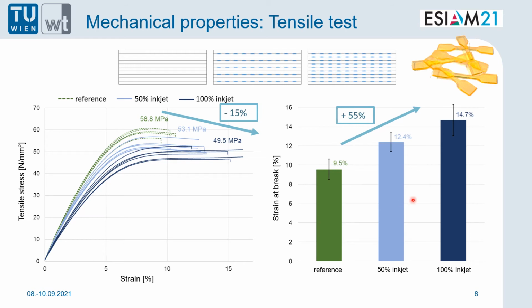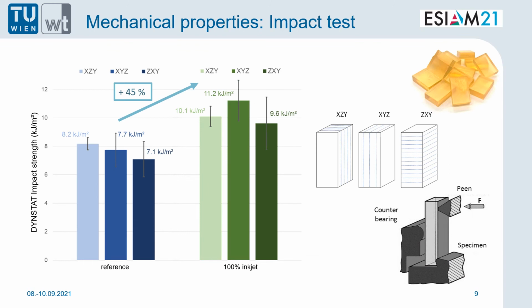We jetted different amounts of ink inside of the parts and observed a linear behavior with increasing ink amount. While tensile strength was reduced by 15%, an increase of up to 55% of the strain at break was observed. Also for impact tests, where we had to conduct Dynstat tests because of the small building platform, we gained similar results. So there was an increase of the impact strength with increasing ink content, and this was true for each printing direction.